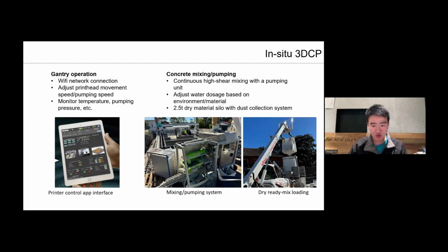For this, we also run a 2.5-ton dry material silo, which feeds material into the mixer. The level of the silo needs to be carefully monitored. When the level is low, another 1-ton bulk bag can be loaded in with a forklift on site. We also have a dust collection system for the loading process, because dry material handling is very dusty on site. We care about people's safety and making a green environment on site, and we must have a dust collection system for that.